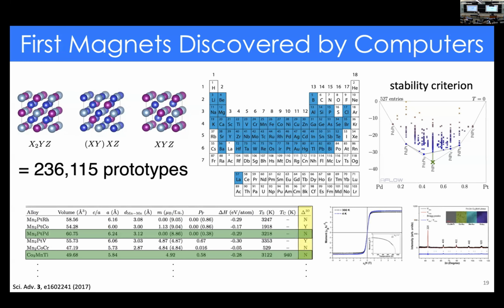We used this stability criterion. We basically asked whether that distance is greater than 30 meV. That's bigger than the 25 meV threshold that I defined earlier, so that's a really big gap. We used that criterion to see which ones were stable, and we found we actually had 4 candidates. We tried them experimentally, and 2 formed. It's 50%, which is not a very good amount in a test, but that's super for materials discovery. We went down from possibly hundreds of thousands of possibilities to 4, which is a manageable number of experiments to try.